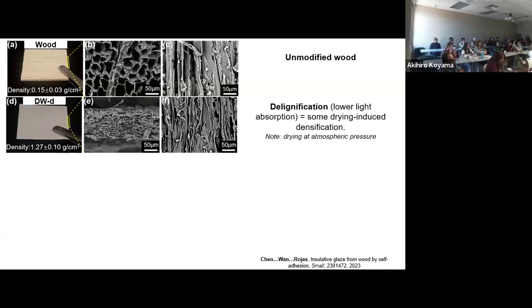Then after delignification, of course, the density will increase. The cross-section signals the fact that the material becomes densified. But here the secret, once again, is in that process: what we did was to add water and remove water. And that removal of water led to this process of densification. It's a drying-induced densification by something called capillary forces that we can maybe expand on, but maybe we have no time now. But by capillary forces, surface tension forces, very high pressures will be applied here, and the material will be densified. That's the delignification alone.